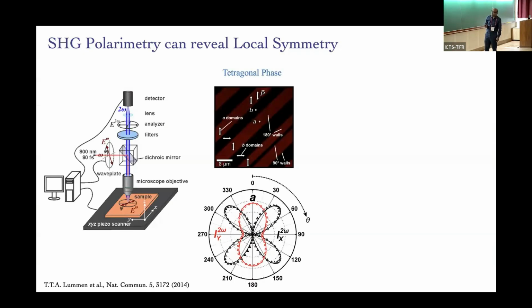We figured out they're tetragonal because we could go to a point A or point B and do what is called polarimetry. So you could rotate the polarization of the incoming light, that's that circle, that's the same as this, and you can detect the output blue light at various polarizations. So red versus black is two orthogonal polarizations. And you see all these beautiful peanut and cloverleaf and so on, nice shapes. They have some information about the crystal structure, and you can fit them. Solid lines are theory, and from that I can tell you this is 4mm. If you know point groups, this is the 4mm point group. Okay, beautiful, as expected, boring in some sense.